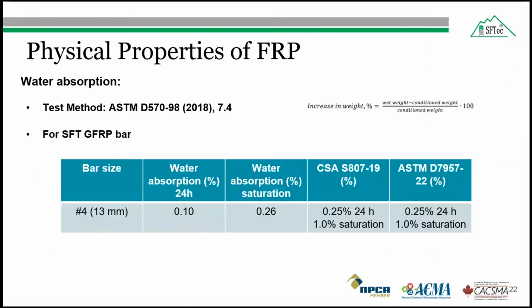And for the SFTec glass fiber reinforced polymer bar number 4, the average measured water absorption at 24 hours was equal to 0.1%, which was lower than the 0.25% requirement in both the Canadian and American codes. And at saturation, it was 0.26%, which was lower than the required values.